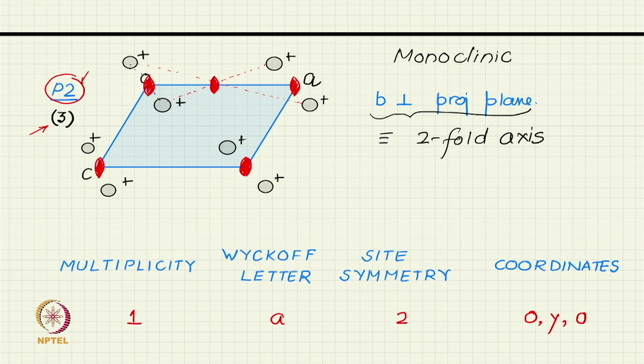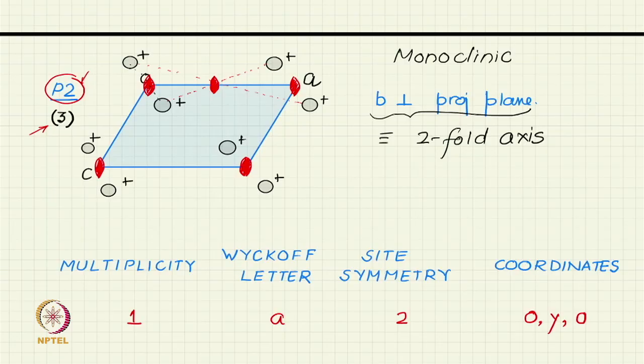This property we are familiar with from when we were looking at the plane groups also: whenever you have a twofold axis passing through a lattice point, then in every translation direction there will be another twofold axis at half the translation. So, similarly you generate a twofold at c by 2 there, a twofold here and a twofold here. And note that the diagonal of this parallelogram is also a lattice translation, that is the A plus C translation, and there also the same principle will act and you will get a twofold in the center. So, these twofolds all get generated by our starting twofold.